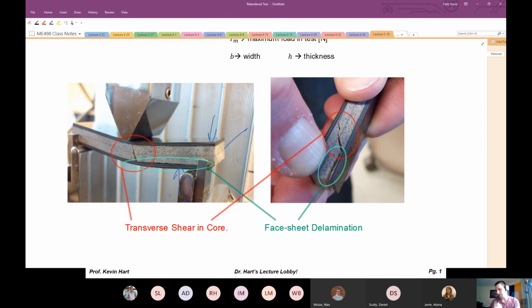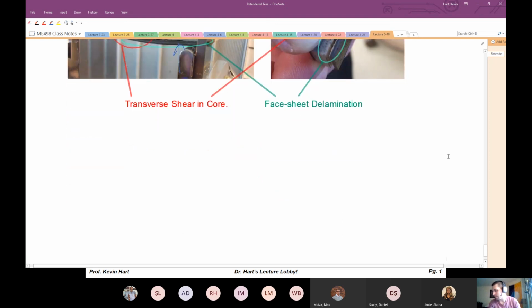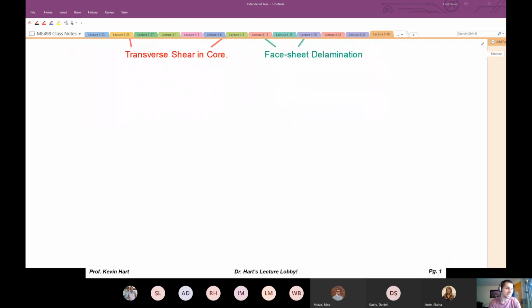I wanted to show you this short beam shear test because it's the most common test used in industry to describe the strength of the interface. You load this up, and then there's some load value at which this thing fails. And so you can compare the maximum load value of one composite to the next with this short beam shear test. Obviously the sample that has the highest load has the best interface between the core and the face sheets. There are some standards associated with short beam shear testing that I've uploaded to Blackboard, and I'd urge you to look at those standards and at least be familiar with them if you ever need to use them in industry in the future.